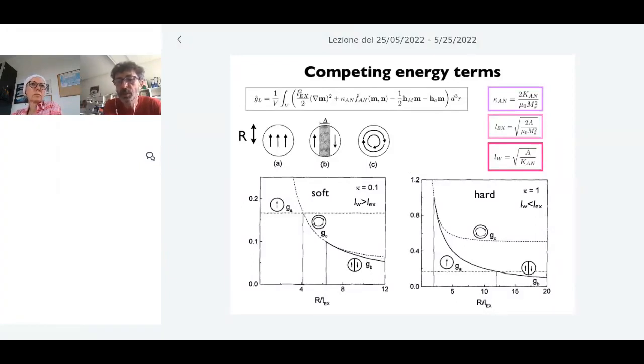So you imagine that the magnetization is free to adapt to any change without spending too much energy. And so what happens? We discussed this. The magnetostatic, let's say, demagnetizing field depends on whether we have a change of magnetization at the surface. But if we keep the magnetization always parallel to the surface, not perpendicular, then this demagnetizing field is minimized.